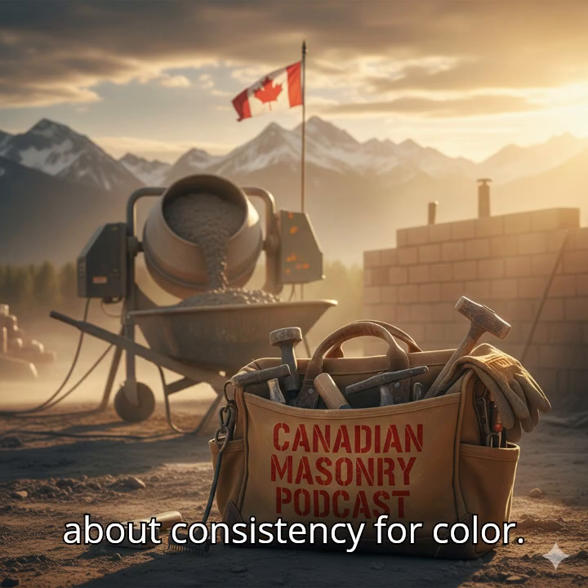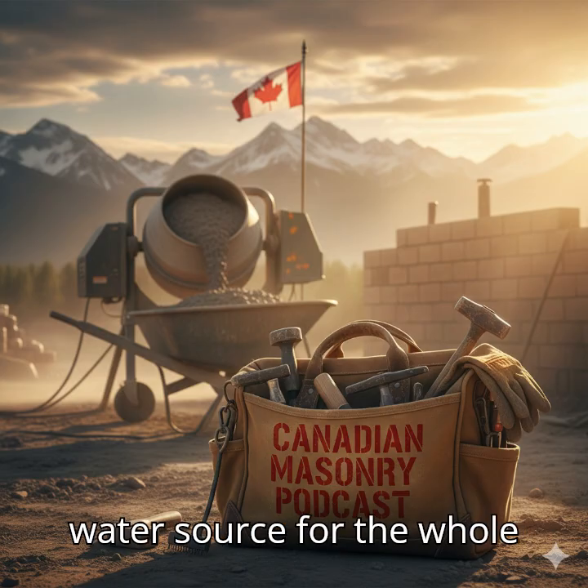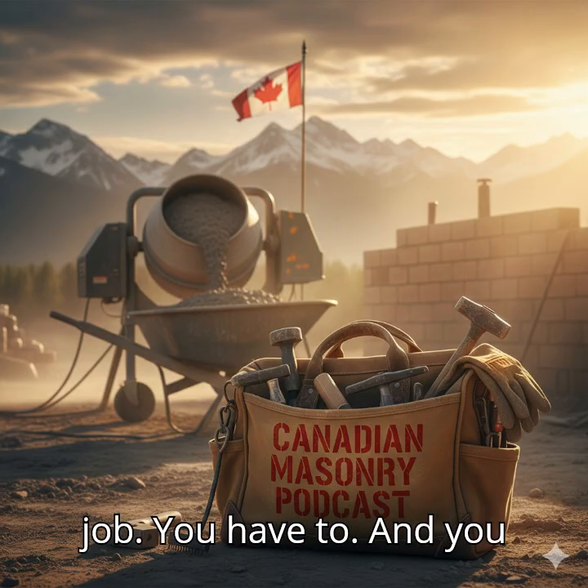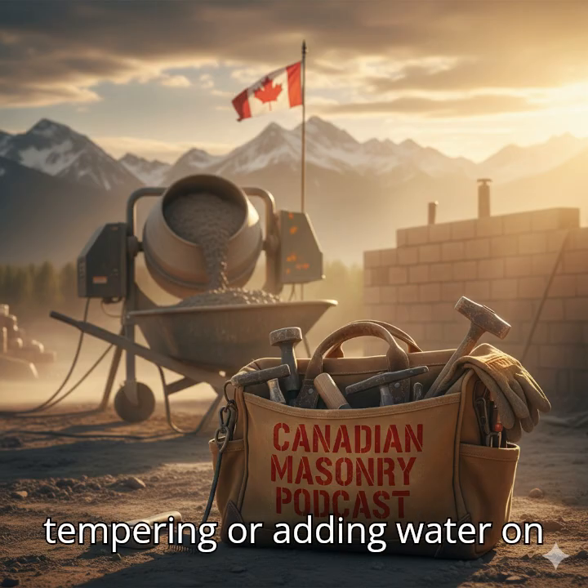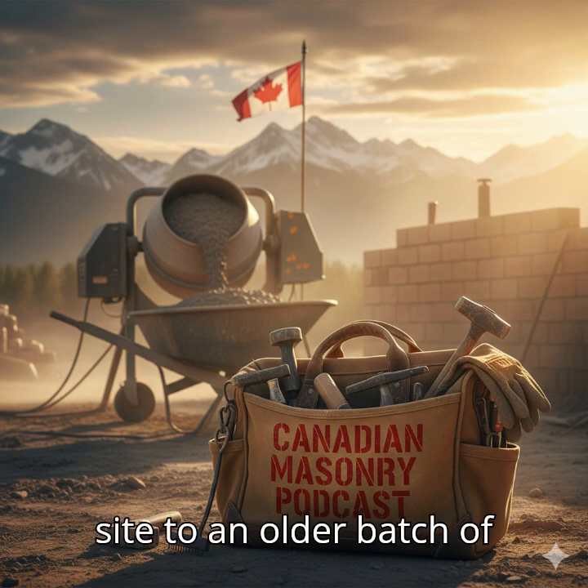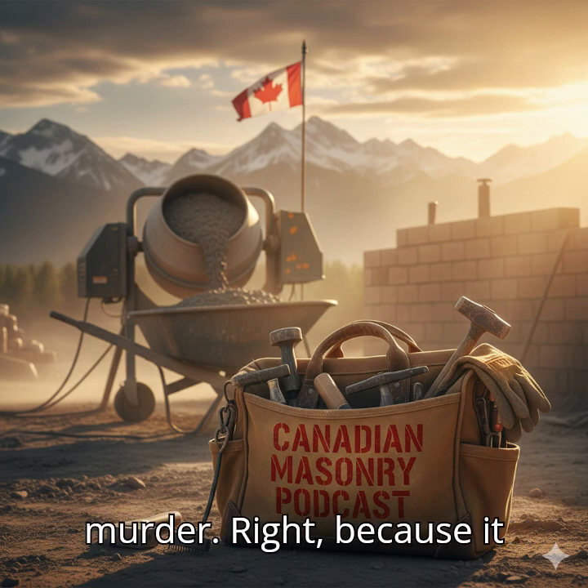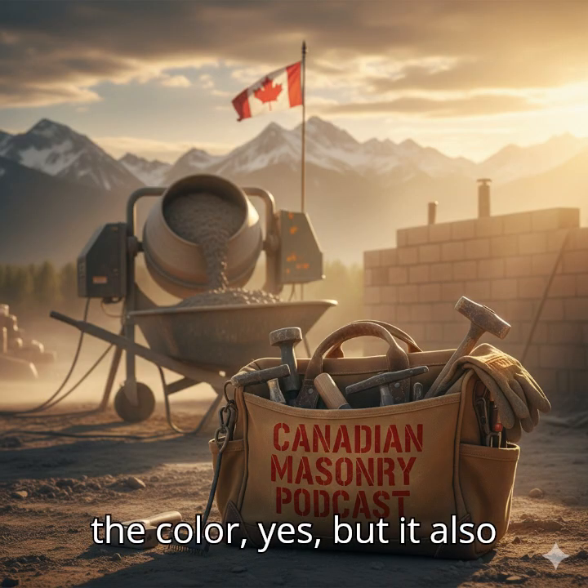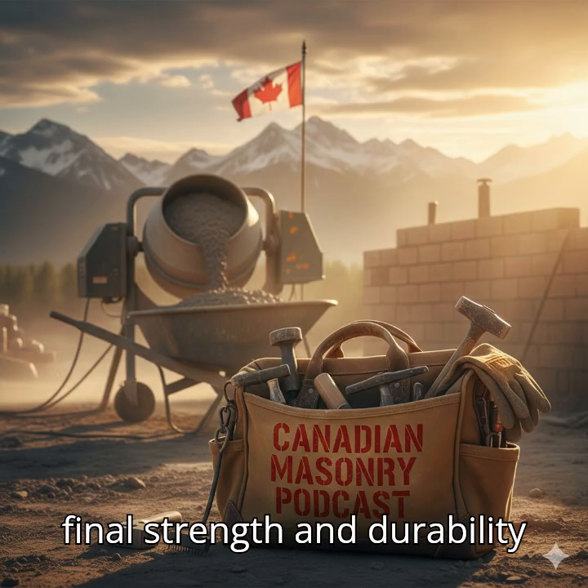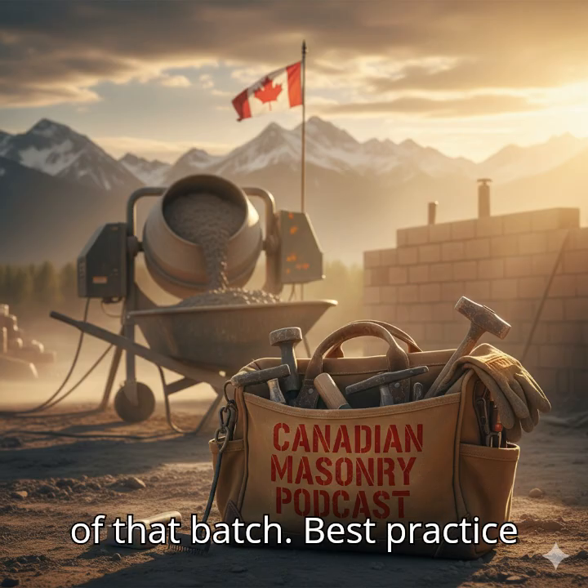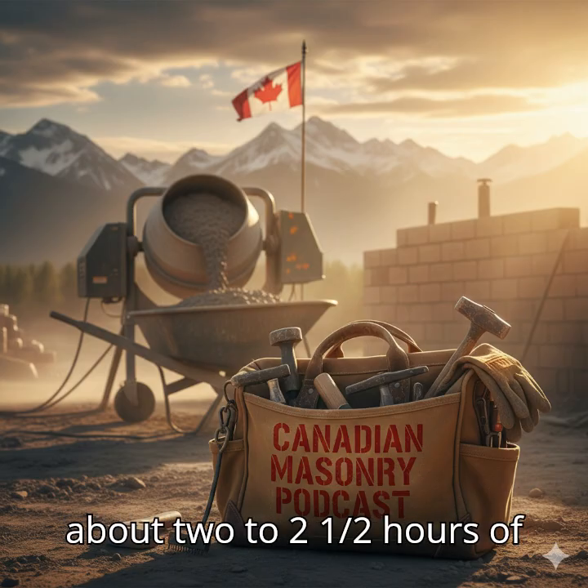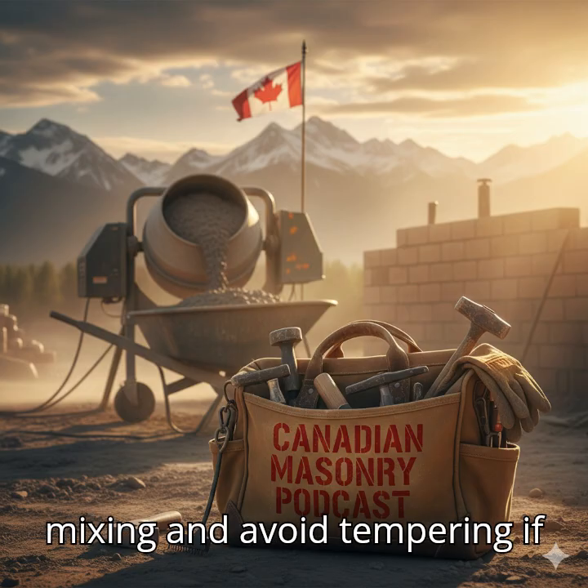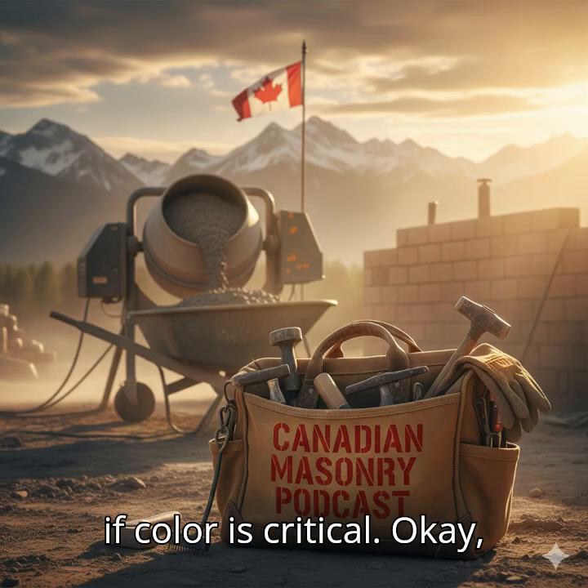We talked about consistency for color. That means using the same water source for the whole job. You have to. And you have to be careful about tempering or adding water on site to an older batch of mortar. Right, because it changes the color. It changes the color, yes, but it also increases the water to cement ratio, which reduces the final strength and durability of that batch. Best practice is to use your mortar within about 2 to 2.5 hours of mixing, and avoid tempering if at all possible, especially if color is critical.